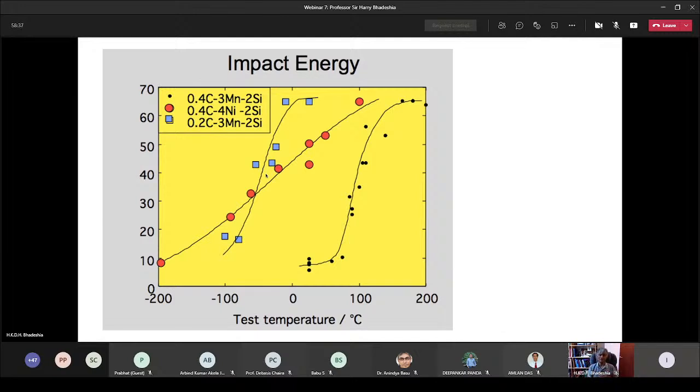without compromising the toughness. So what I want to emphasize is that, going from the mechanism of transformation, understanding from an optical micrograph that you have large islands of austenite which will decompose to martensite under stress and therefore make your material brittle, and then using the simple T0 analysis without doing any experiments, you can predict two alloys which should behave much better, and they do in practice.